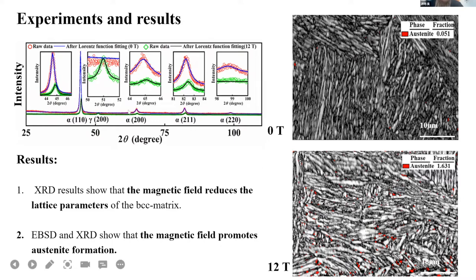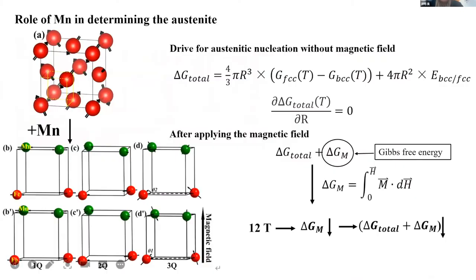So we did different experiments, such as XRD and EBSD, to prove the first result, that the magnetic field reduces the lattice parameters of the BCC matrix. And the different experiments show that the magnetic field promotes austenite formation. Because there is manganese in our experiment, and manganese shows anti-ferromagnetic characteristics.